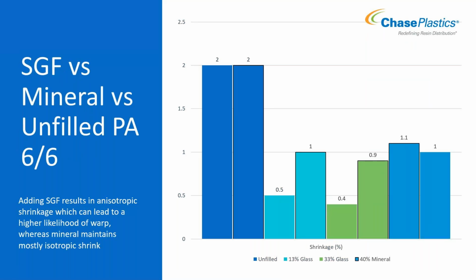And then we bring in the same data but include the mineral as well. We said that mineral does not add to anisotropic shrinkage - it tends to keep it more isotropic. You can see with the 40 mineral, you're at 1.1 and 1%. This is because minerals tend to not be cylindrical in shape - they tend to be more spherical, with some variants, but generally spherical, so you're not going to have that issue with it lining up with the flow when it's running. So you don't experience that as a problem.